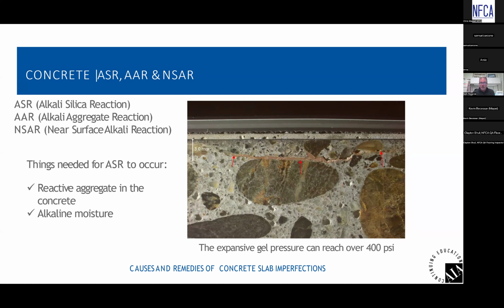Even if you reprofile the surface, that reaction could happen, and it could cause a failure in the new material that you put on the surface of the concrete. You know, short of pouring another 4 inches of concrete over the existing concrete and dealing with elevation issues, you can't just put a thin coating over top of this and expect ASR not to occur again. You really need to eliminate the source in this situation, which would be water. So the solution is to break out the jackhammer? Yeah, really, unfortunately, or pour a topping slab over top.